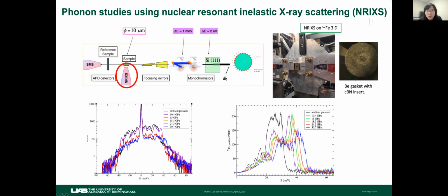And in one of the runs, we used a miniature panoramic DAC with 2 APD detectors placed next to the sample. Because the signal is coming out of the gasket, we use a beryllium gasket with a cubic boron nitride insert. This insert is to increase the thickness of the gasket and also maintain a decent thickness on the sample.